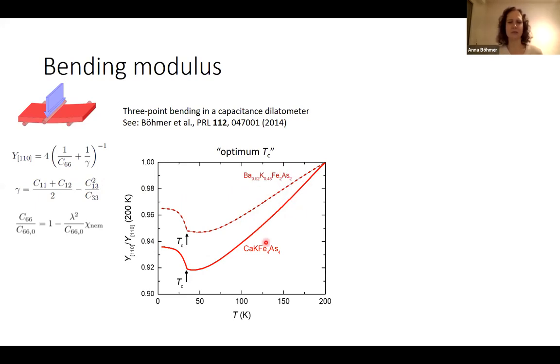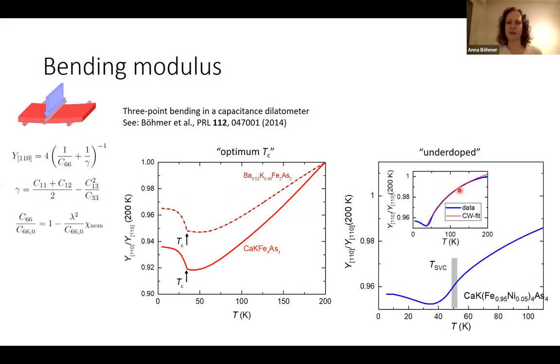Very similar temperature dependence. On the other hand, for the nickel-doped one, or what would be an underdoped one with a magnetic transition, I do know what will be the temperature dependence of the Young's modulus if there's a Curie-Weiss-like temperature dependence of the nematic susceptibility, and that's what this red curve shows you, and it works very well. So here again, we have evidence for a Curie-Weiss-like divergence of the nematic susceptibility. There is a very curious, very subtle anomaly at the spin vortex crystal magnetic phase transition here.